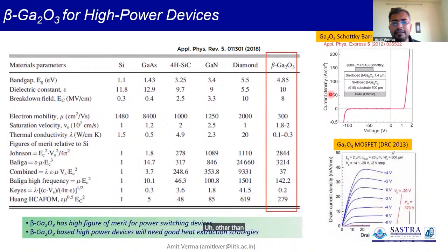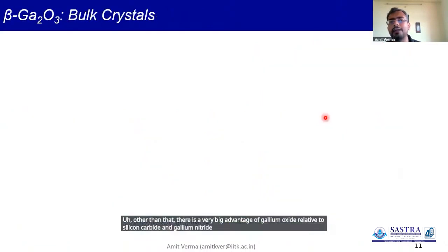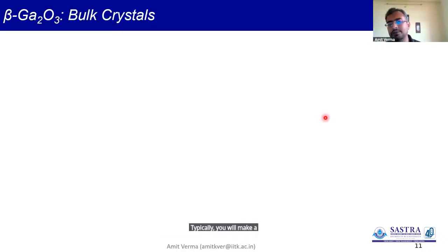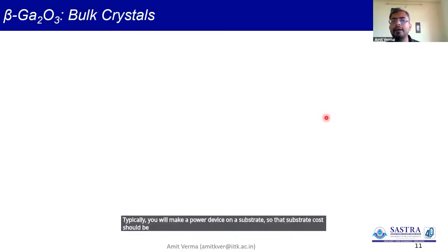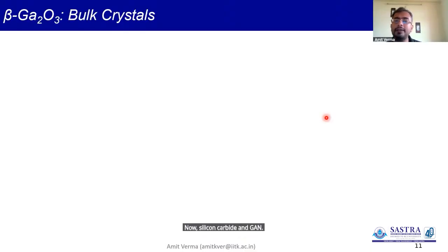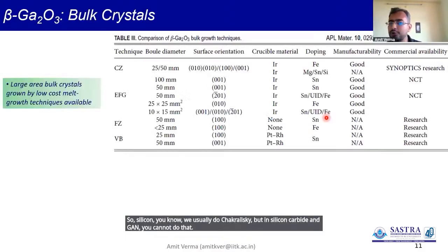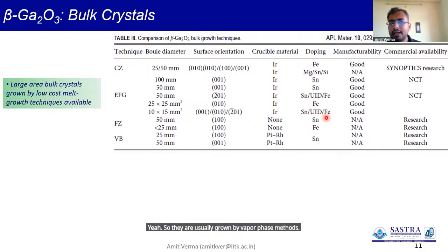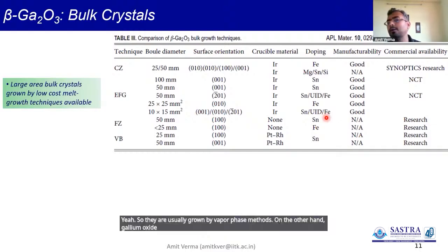Other than that, there is a very big advantage of gallium oxide relative to silicon carbide and gallium nitride. That is the availability of bulk substrates. Typically, you will make a power device on a substrate. So that substrate cost should be low enough, and it should be available in large area. Now, silicon carbide and GaN actually cannot be grown from melt like Czochralski. Silicon, we know, we usually do Czochralski, but in silicon carbide and GaN, you cannot do that. So they are usually grown by vapor phase methods. On the other hand, gallium oxide can be grown by melt growth.